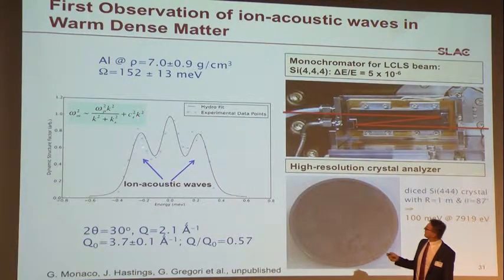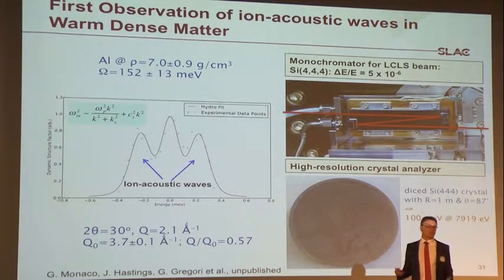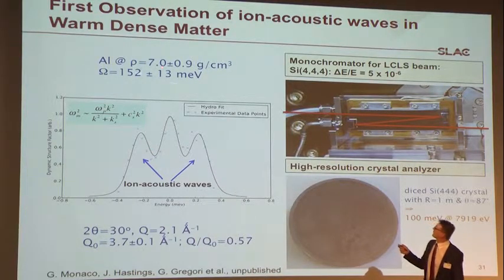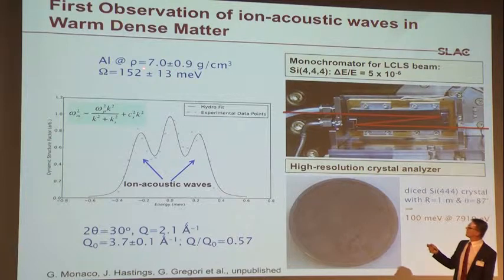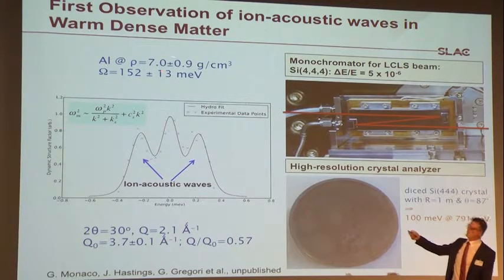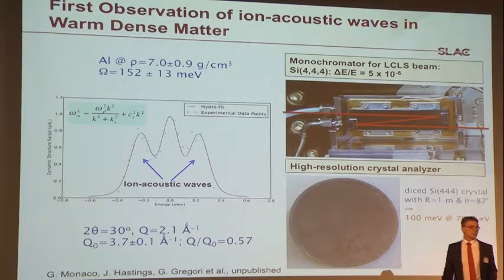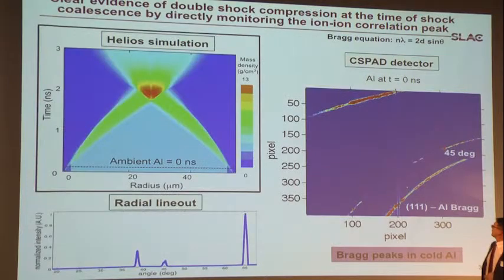That means the frequency shift of the ion acoustic modes was also dependent on density. But actually, we find a density that was independently analyzed by a different group, namely in Oxford. They found 7 g/cc, which is exactly what we found with plasmons in Stanford. So this is a very nice agreement. So let's now look at temperature, and let me explain to you why we believe we can measure temperature in